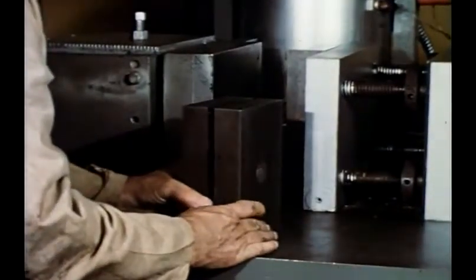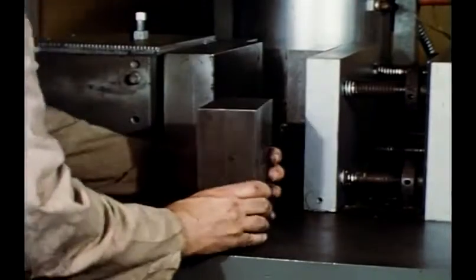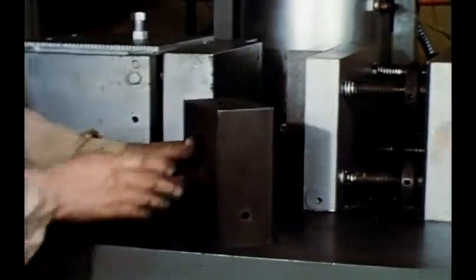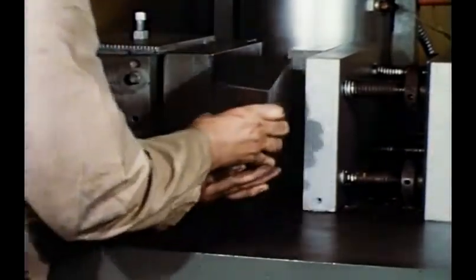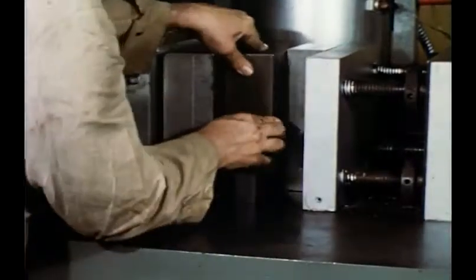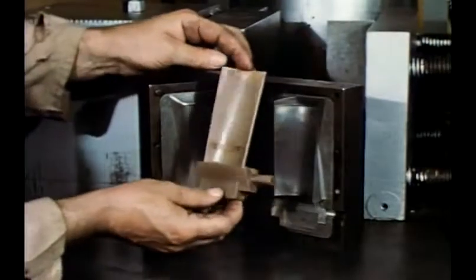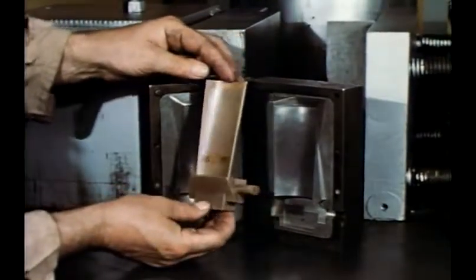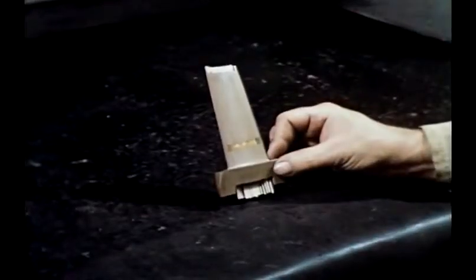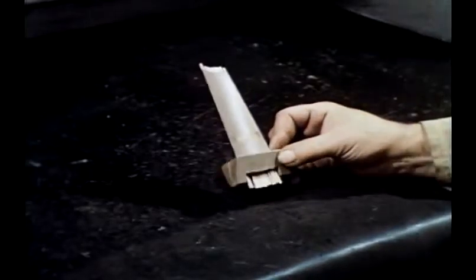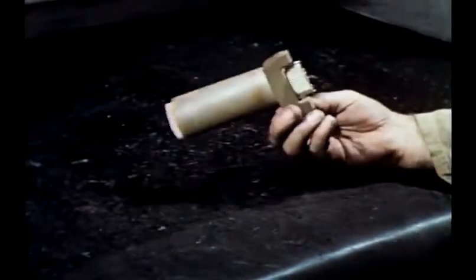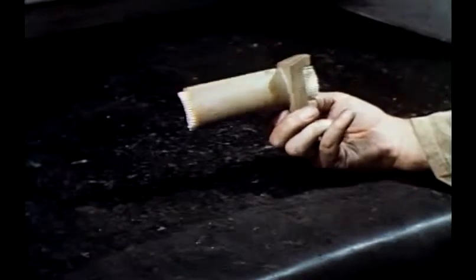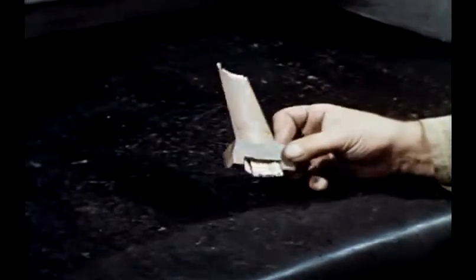A casting pattern is made by closing the dies containing the ceramic tubes, clamping the dies in a wax injection machine, and injecting molten wax under pressure. The wax pattern containing ceramic tubes is removed from the die and excess wax is trimmed, leaving a light wax film on the exposed ceramic tubes to permit freedom of movement due to expansion.